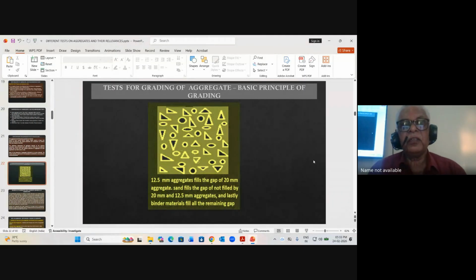That means 20 mm, 12 mm, sand, and cement are used. The purpose of providing 12 mm is to fill the gaps which 20 mm cannot fill. Sand fills the remaining gaps within the 12 mm aggregate, and whatever is not filled by sand is filled by cement or cementitious material. So the purpose of grading is to combine all these aggregates so that there is no gap inside the concrete, producing a dense concrete.